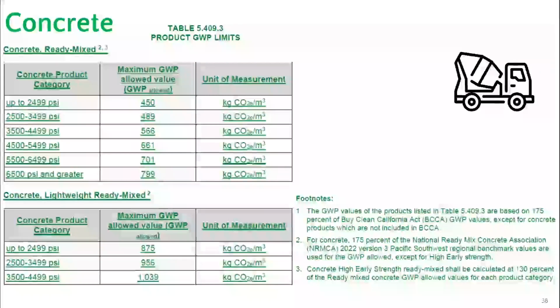have higher GWPs. In addition to that, in general, most lightweight concretes will have air, as air is the lightest thing we can put in there. And when we add air to concrete, it has a tendency to make it a little weaker. So we compensate with additional cement or cementitious materials. The other thing to note is that the product category table goes up to 6,500 PSI and greater. So as we see more 8, 10, 12,000 PSI concretes, they'll fall in that 6,500 PSI or greater table.